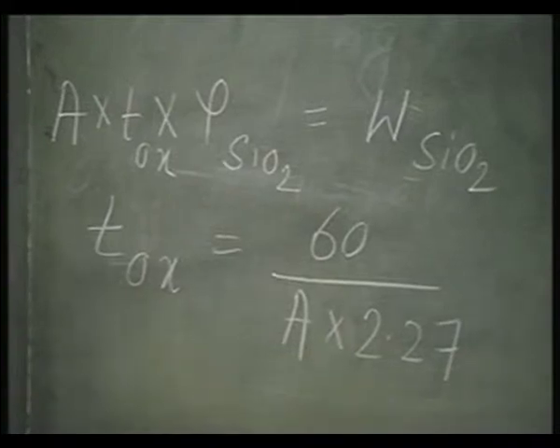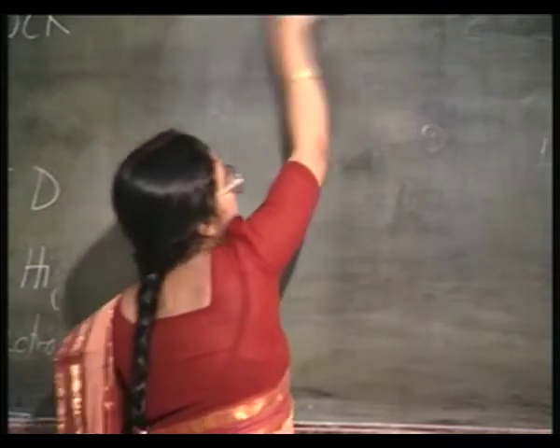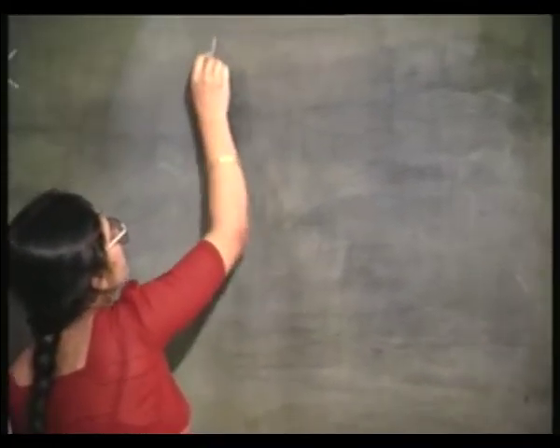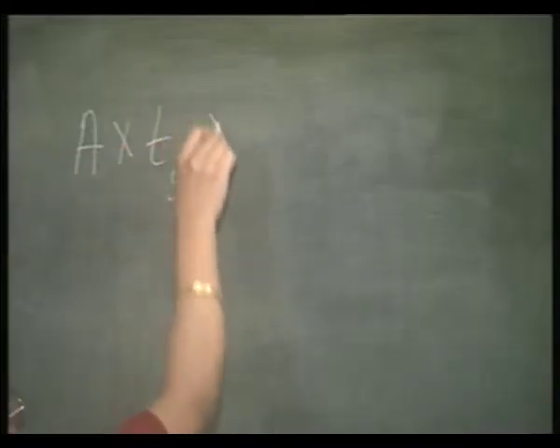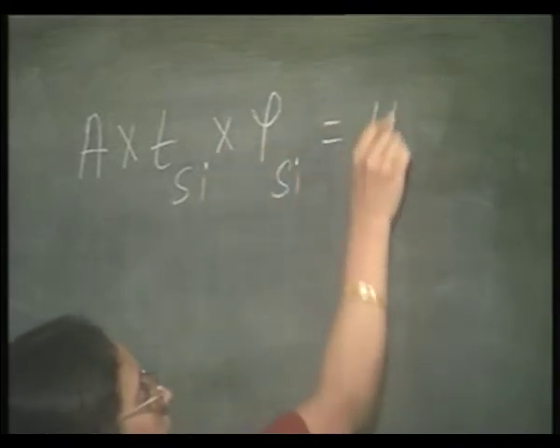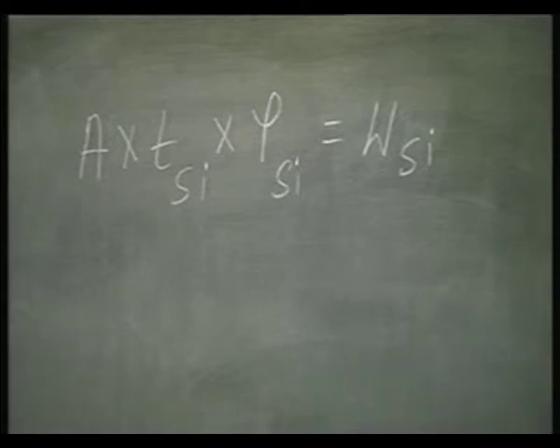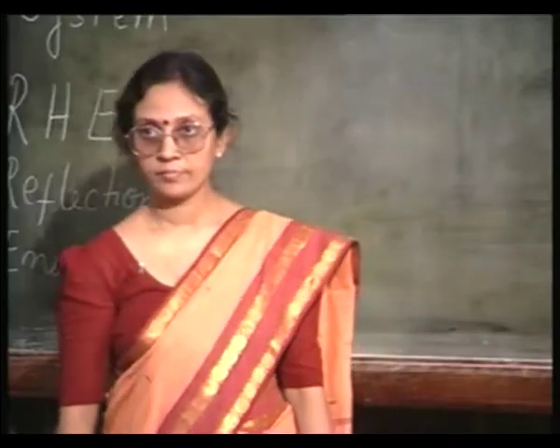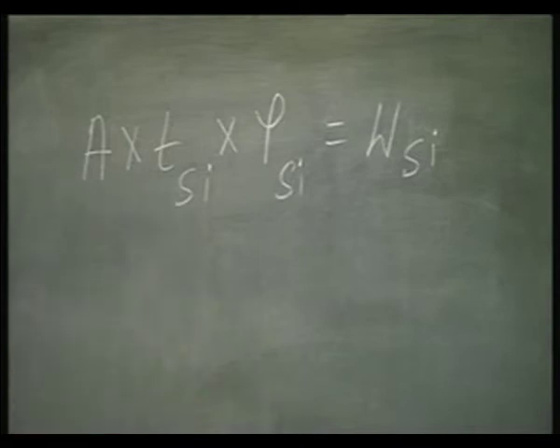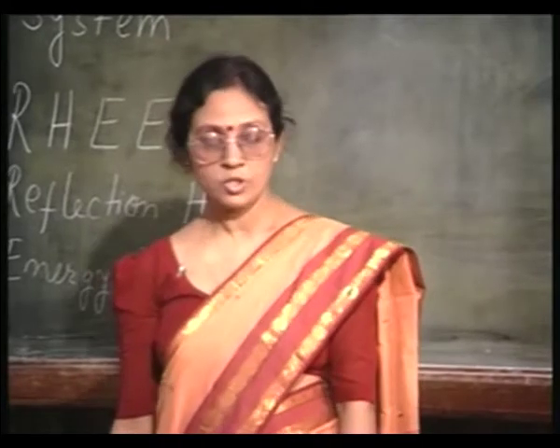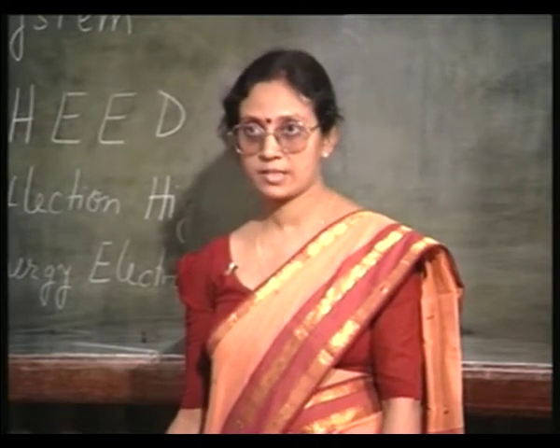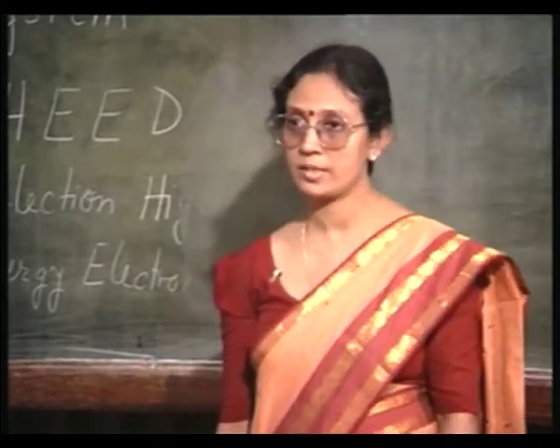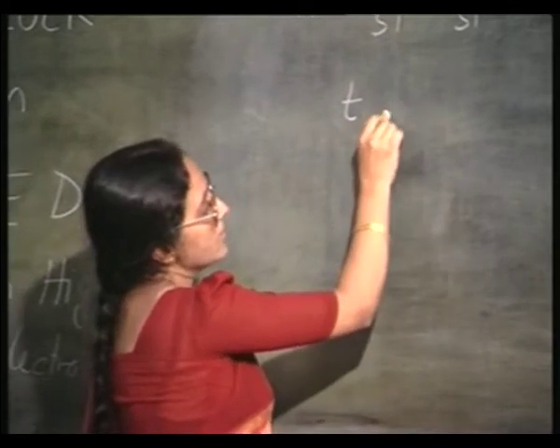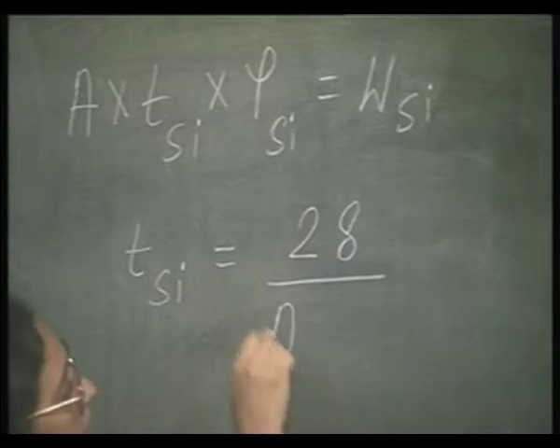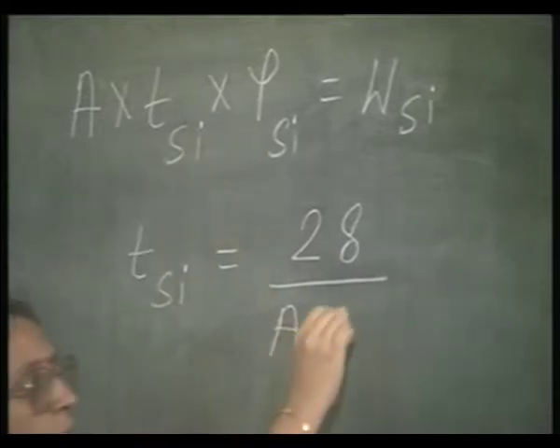On the other hand, similarly, I can write for the silicon, the equation is like this. T suffix Si is the thickness of the silicon that is consumed. So, I know that 60 grams of silicon dioxide is formed by consuming 28 grams of silicon. So, I could say this TSi is therefore equal to 28 by A into the density of silicon, and that is 2.33.